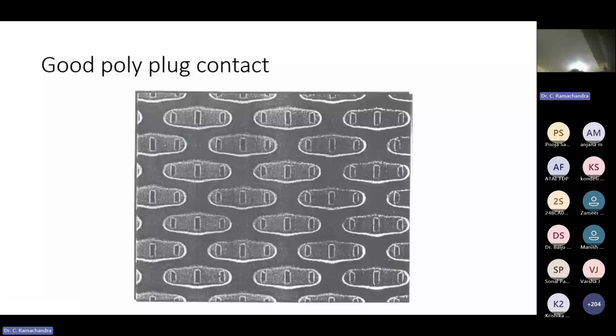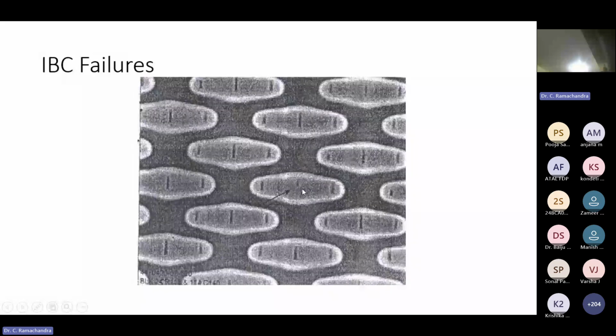Then when we etch completely, see, this is the impression that will tell that it had enough penetration and made a good penetration. When you have a good impression like that, my polyplug is good. But if you go to the failed device, you can see poor impression. That means contact was marginal. That was creating damage. So this was a very interesting technology we developed 20 years back, and it was widely used in our industries.